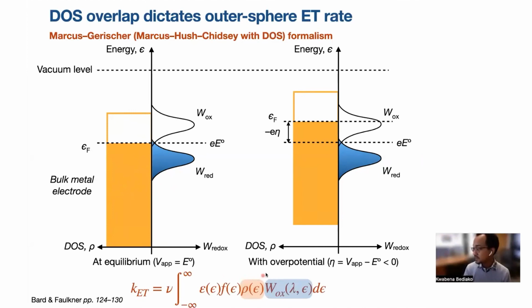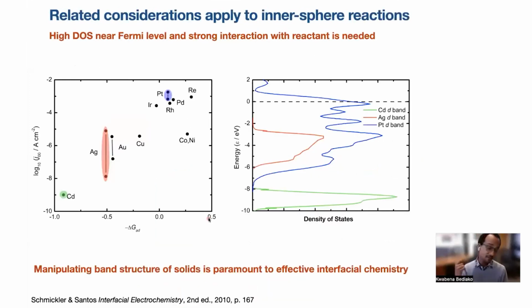And as described in that equation, that applies simply to an outer sphere charge transfer reaction where there's no bond formation process. But even for catalysis, the electronic structure of the electrode is very, very important and can actually be used to explain trends in hydrogen evolution activity across the periodic table. I won't go much more into that other than just to drive home the main point of this whole introduction, which is that manipulating the band structure of solids is very, very important to understanding and more efficiently driving interfacial chemistry.